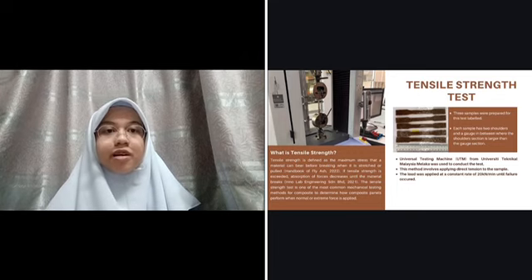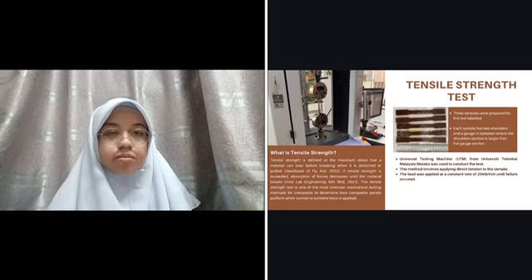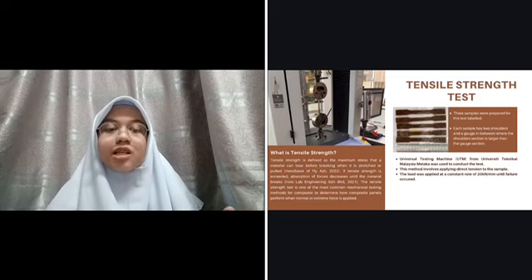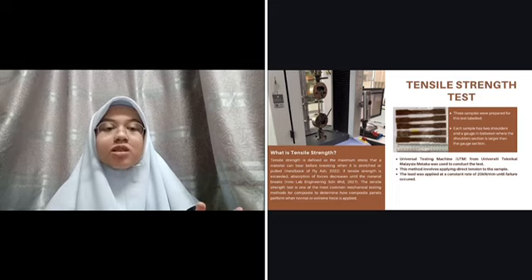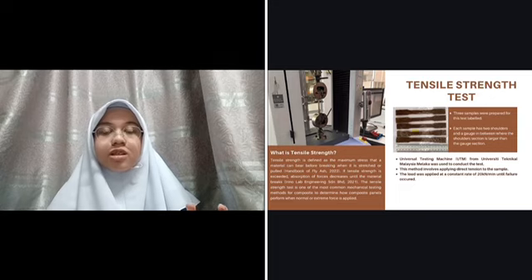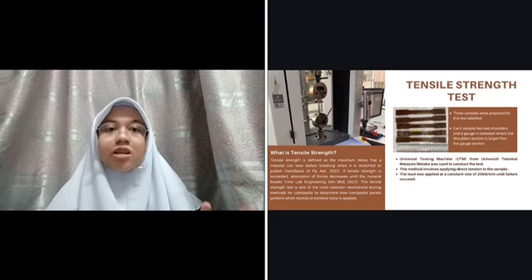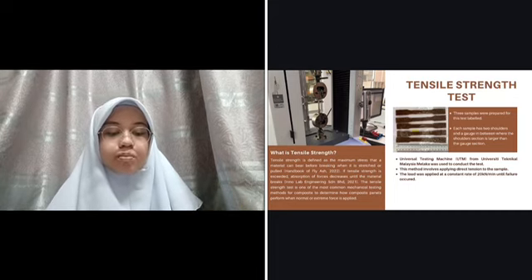The next test we conducted was the tensile strength test. Tensile strength can be defined as the maximum stress that a material can bear before breaking when it is stretched or pulled. We conducted the test on our composite panel to determine how it will perform when we apply extreme force to it. For this test, we used the universal testing machine from University Technical Malaysia Malacca, and we prepared 3 samples where each sample has 2 shoulders and a gauge in between as shown in the picture on the right.